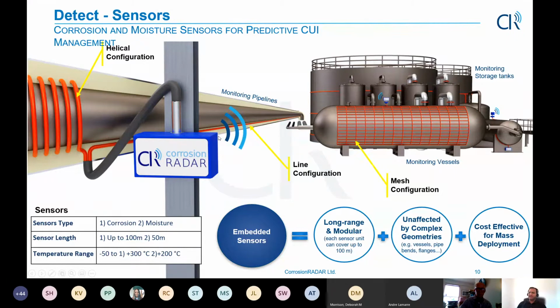And the sensors are deployed inside the insulation, embedded into the insulation in various fashions. For example, if it's a small diameter pipe, we'll put the sensor in a linear fashion at the bottom of the pipe. But if it is a vertical pipe, or large coverage is required, like a large pipe diameter, we'll prefer a helical configuration. Now, as far as pipe is concerned, that's the arrangement. But if we have towers, the rings of the towers are very, very prone to CUI, and we have cases where we have put rings around the tower, and then a large area like a heat exchanger or any pressure vessel we cover in a mesh configuration in a zigzag fashion.